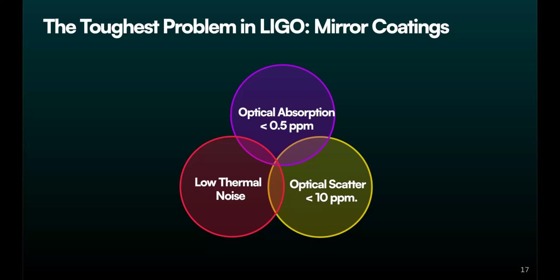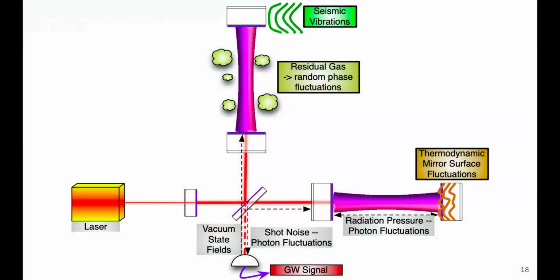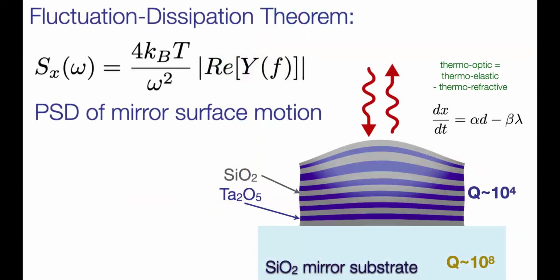So the substrate itself has a mechanical quality factor of 10 to the 8 or more. That means if you ping it, it goes 10 to the 8 cycles before the energy goes down by half. So that's really, really good. But that's just glass. And to make it into a mirror, there's a thin film on the front surface. And that thin film moves back and forth. As I said, the substrate is 10 to the 8, but the film on the surface only has a Q of about 10 to the 4. And so that means its coupling to the heat bath and the other modes is 10 to the 4 times worse, which is no good.